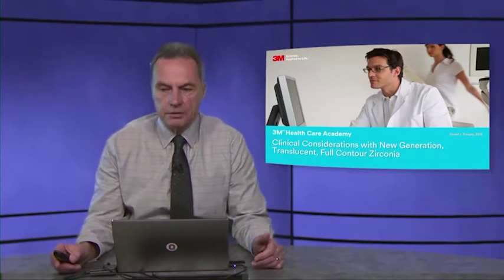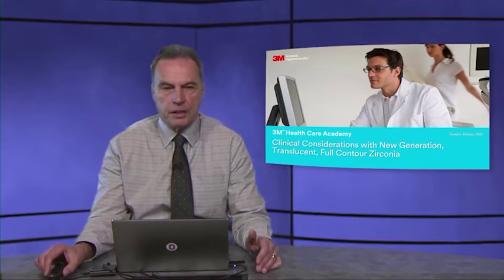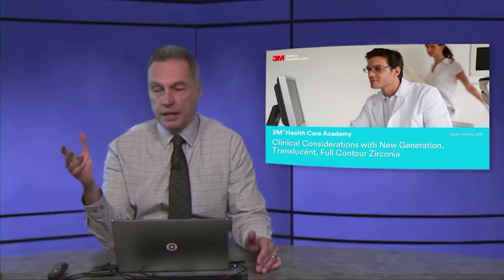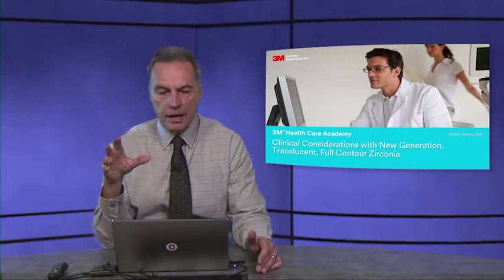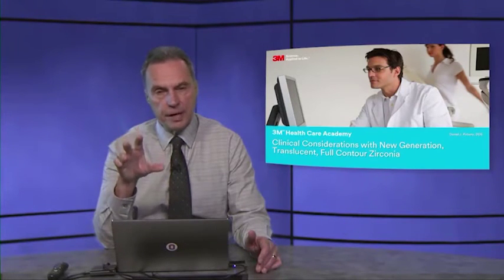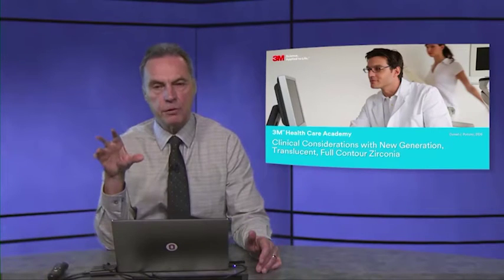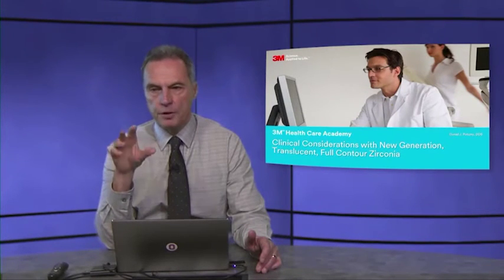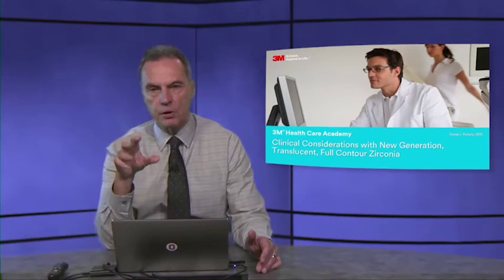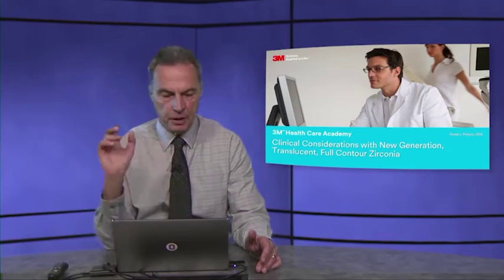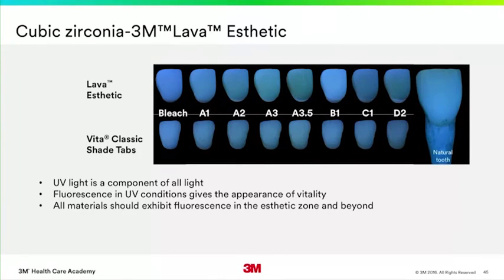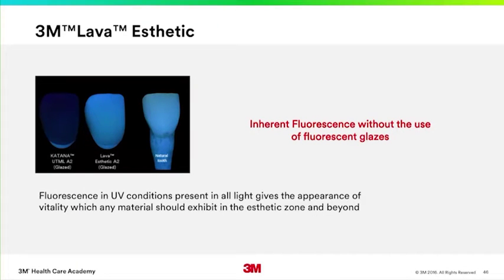More interestingly is the level of fluorescence. Fluorescence is a very difficult thing for a patient to understand, but it's easy for a dentist to understand, because ultraviolet light exists in the presence of all light. It can be in room light, outdoor light. And under UV light, natural teeth fluoresce. A material that approximates a tooth, particularly dentin, should fluoresce in the same way to avoid the appearance of a core beneath the material, or the opacity of the core itself in relationship to the tooth underneath it. In trying to attain this, I think they've done a really good job here, giving this material a nice level of fluorescence that compares very favorably, without the use of fluorescent glazes.